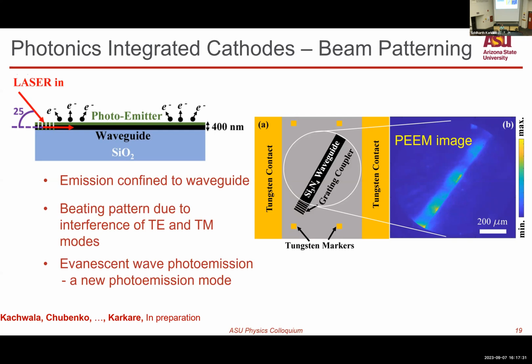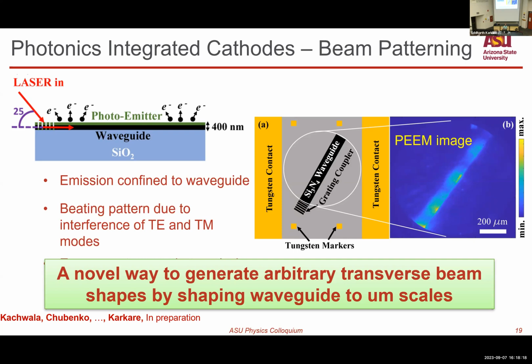Another very interesting thing is this evanescent wave photoemission. It's a new mode of photoemission. Always, photoemission is either done in the reflective mode where light shines onto a surface and electrons come out, or in the transmission mode where you have a transparent substrate, a thin film of emitter, light comes from the back and electrons come out from the front. In this situation, the light is doing neither of those. Light is going parallel to the cathode surface under it, and it's exciting electrons via the evanescent wave absorbed into this emitter. So it's right in between this reflection and transmission mode of photoemission, and it's a new mode of photoemission. And it's also a novel way to generate arbitrary transverse shapes in the electron beam by shaping this waveguide to micron length scales.